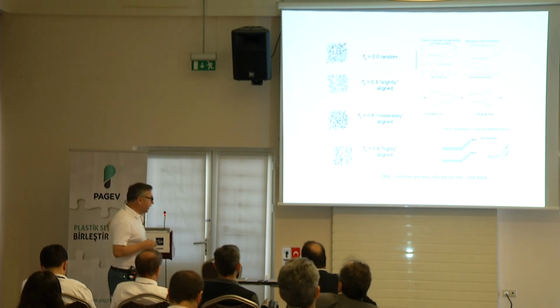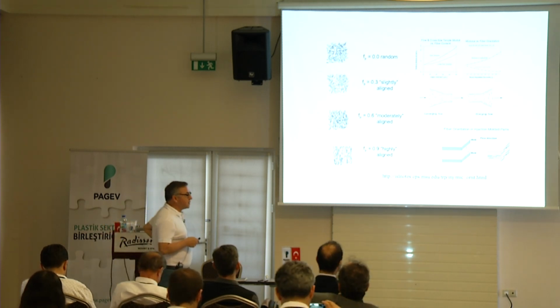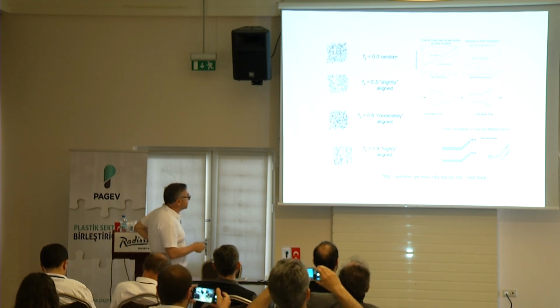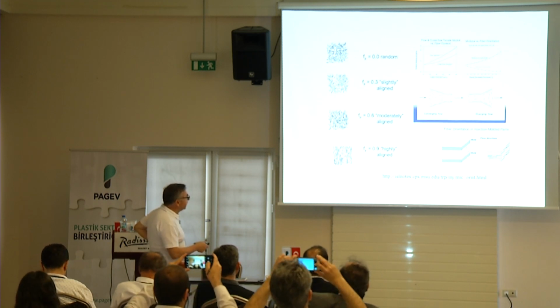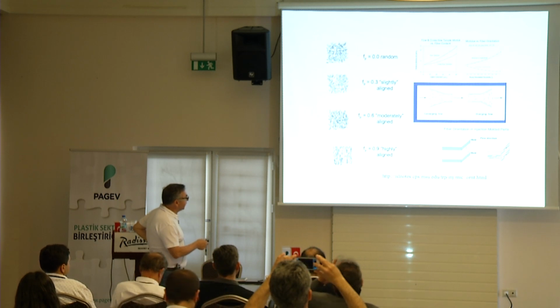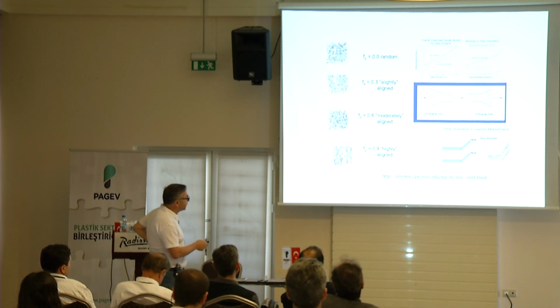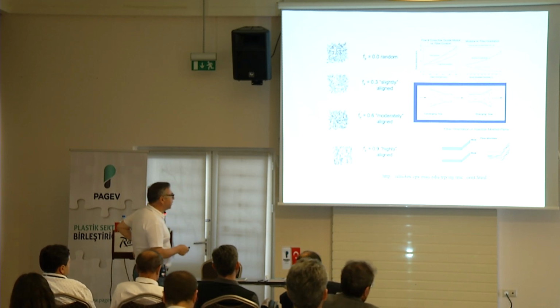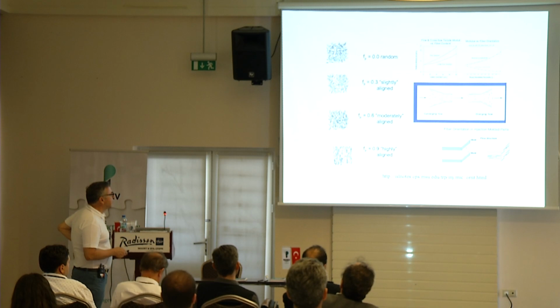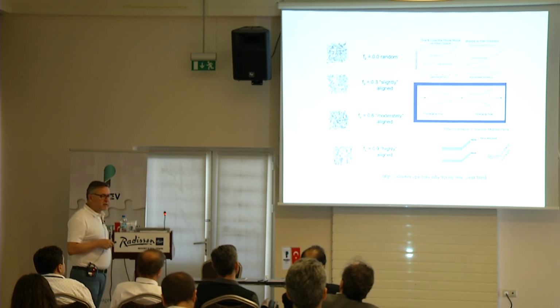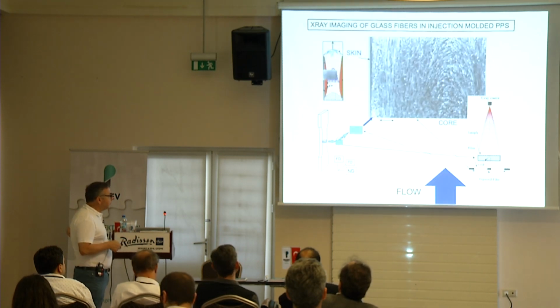So the important thing is that in the case of glass fibers, how does the flow influence the orientation behavior of the glass? If you have a converging flow, the glass fiber tends to orient in the flow direction. If there's a divergent flow, they do go transverse to it. So we've done some studies on these a long time ago. The kind of flow type that the glass fibers undergo in a mold, how complex it is, and whether or not you have convergence and divergence and acceleration will make a difference in their orientation behavior.